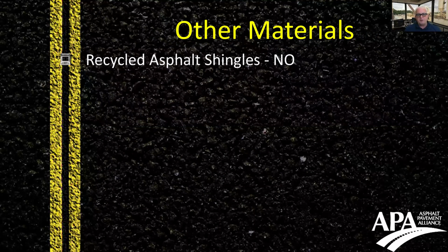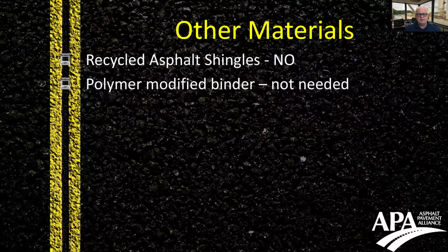So I wanted to go through a list of materials that, depending on your jurisdiction, you may or may not use in asphalt where you're paving parking lots or paving roads. For sport court mixes, you're not going to want to use any recycled asphalt shingles. Recycled asphalt shingles have a tendency toward what I've described as flash stiffening. As the mix cools, the mix can get really, really stiff with asphalt shingles, depending on how it's produced and what kind of complementary products might be used with it. So it's a good idea not to use asphalt shingles.